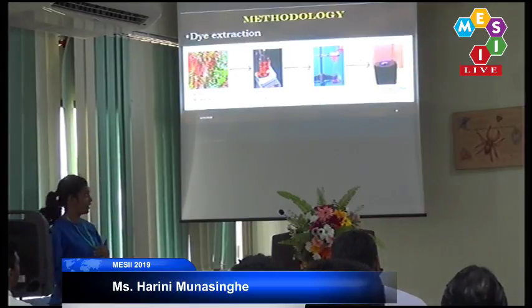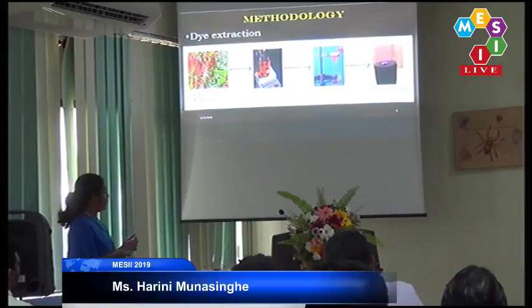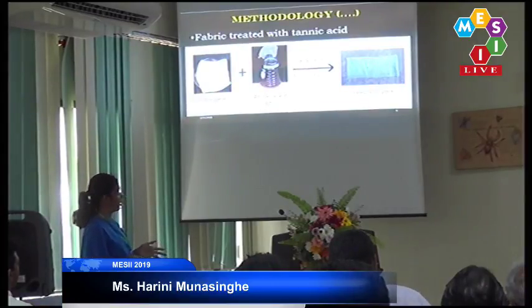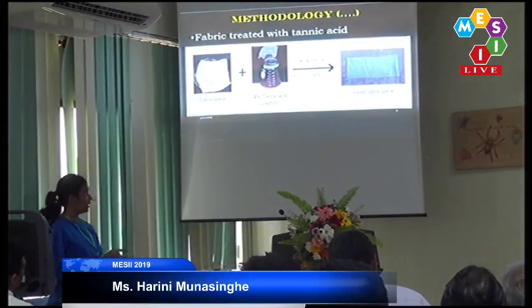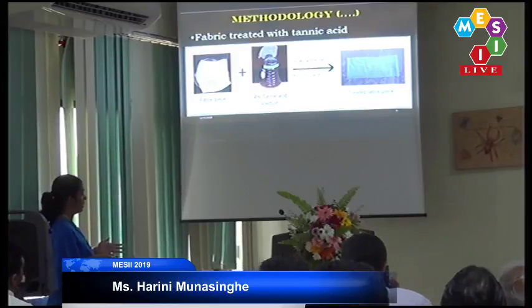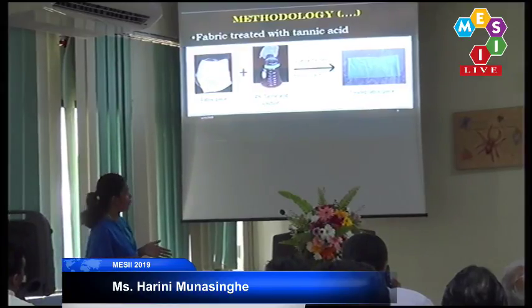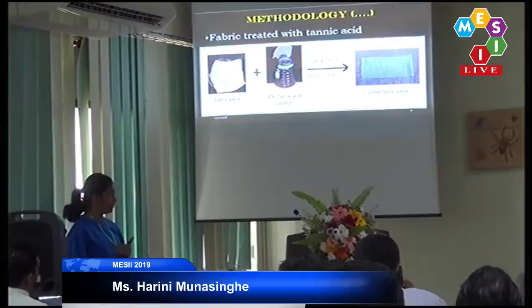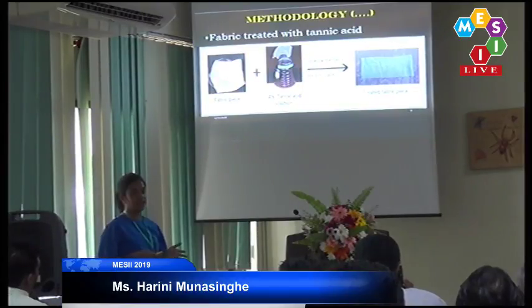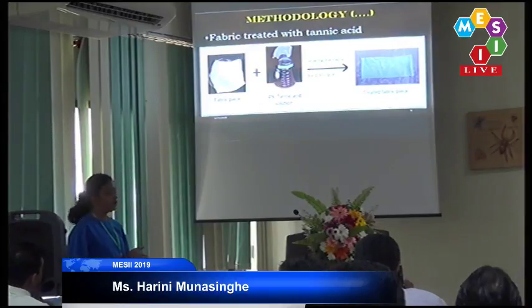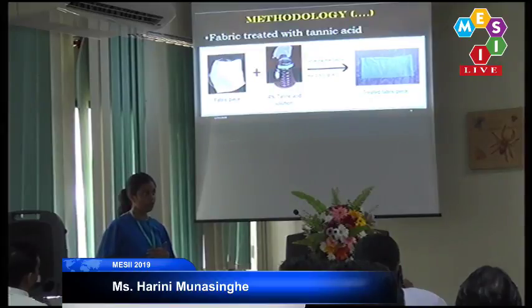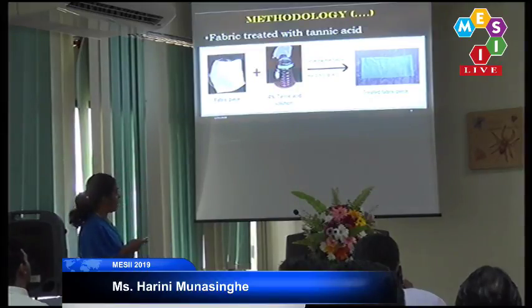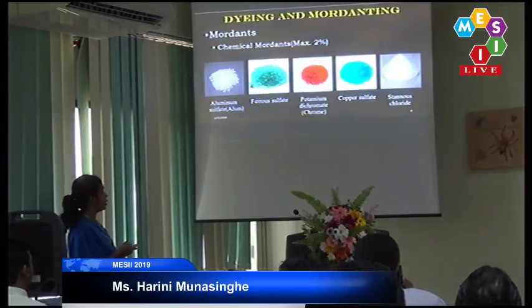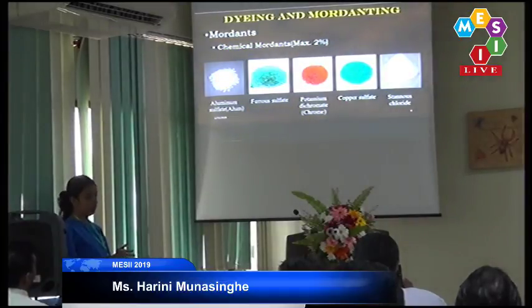and we get the dye extraction solution for the further dyeing process. After the dye extraction process, before going to the dyeing and the mordanting process, we treated the fabric piece with 4% tannic acid solution for 2 hours at room temperature. By treating the fabric piece using tannic acid, it increases the surface activation of the fabric piece and also increases the dyeing ability of the fabric. After the fabric treatment and the dye extraction, we go to the dyeing and mordanting process.